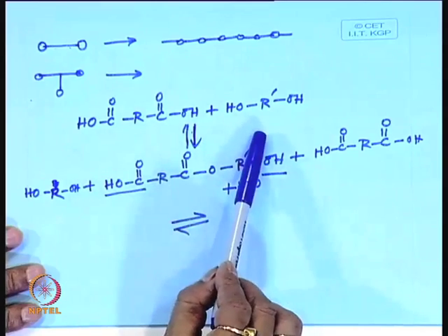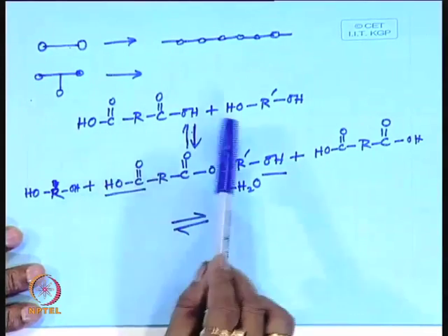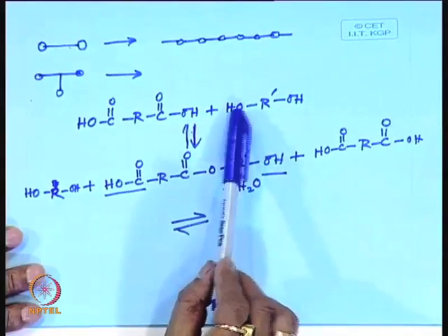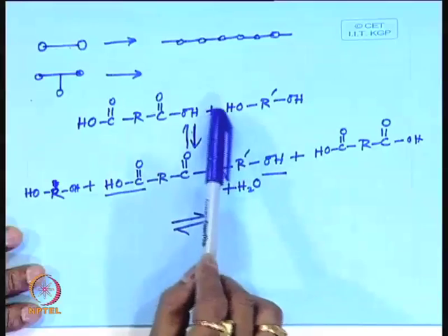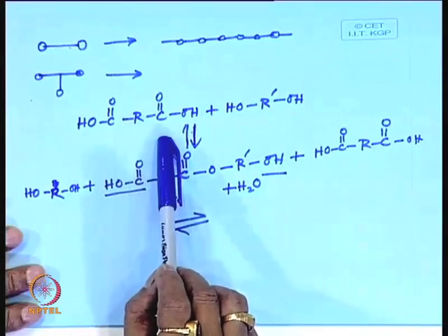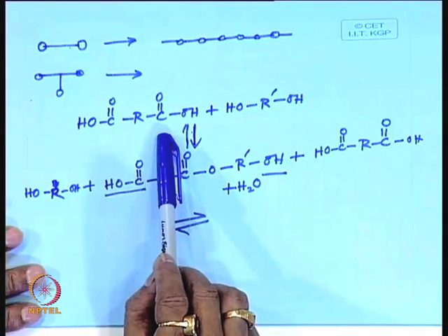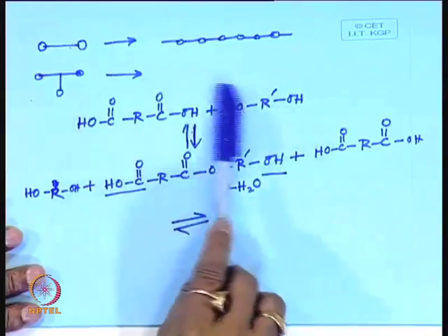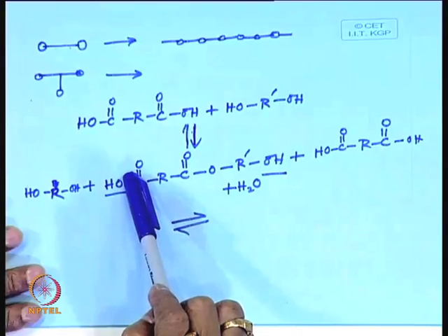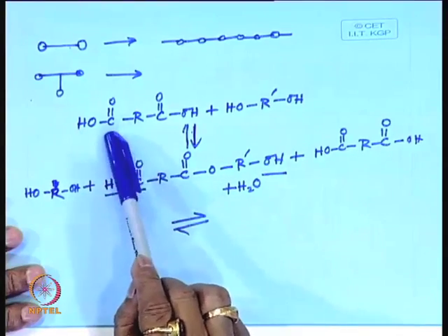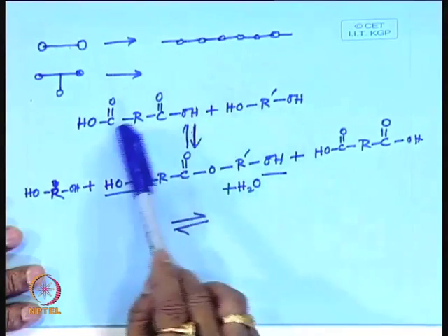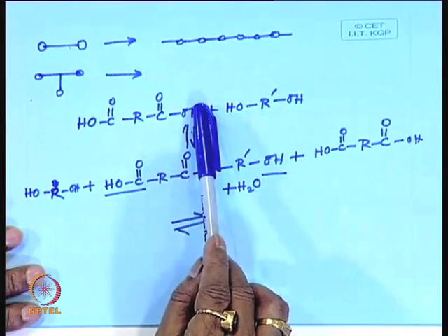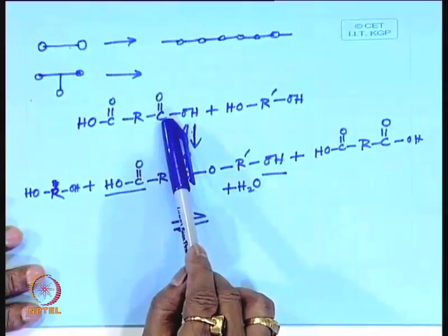These are chemical compounds. So, you have to know the purity level of these things. If they are not 100% pure, then the amount you are weighing, can it be 1 mole exactly? No. So, there are wrong weights, wrong amounts you are taking. So, there is no strict control of the mole ratio of these two reactants. This ratio is called the stoichiometric ratio, stoichiometry between the reactants.